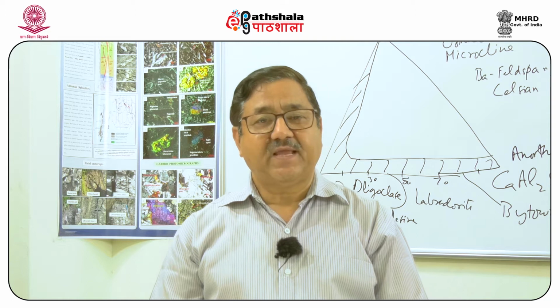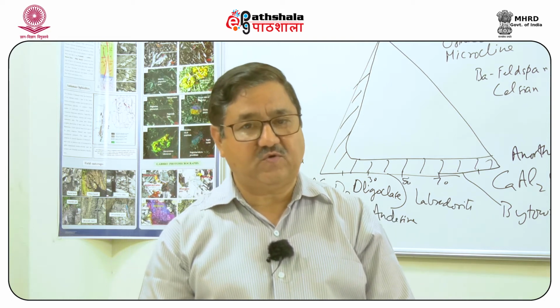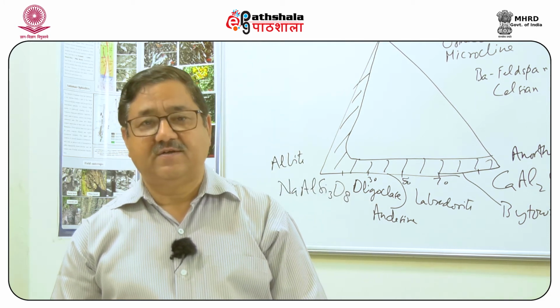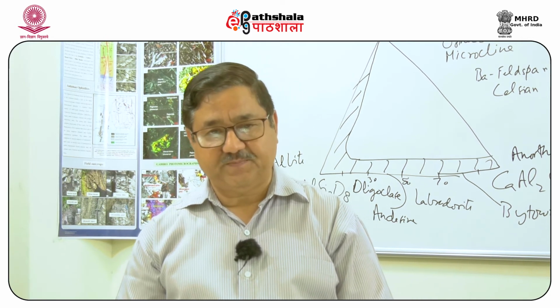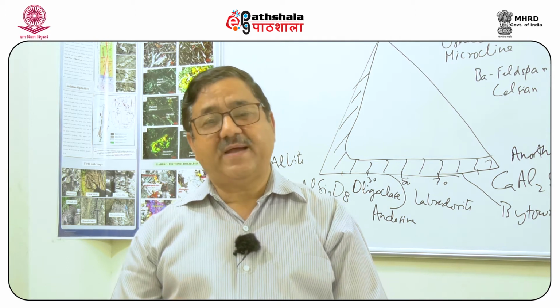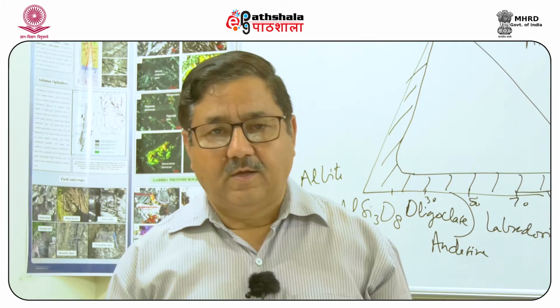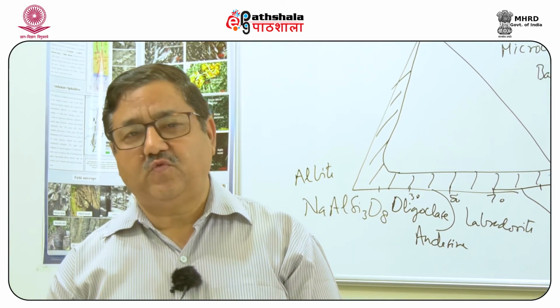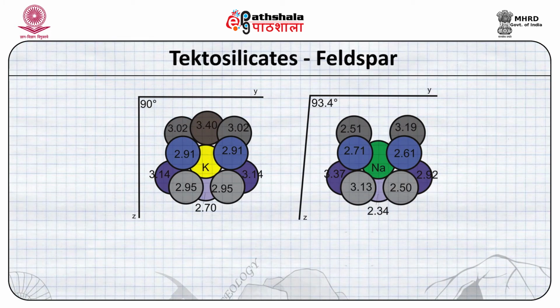These four tetrahedral sites in higher symmetry are represented as two sites, T1, T2. But in the lower forms, they represent four tetrahedral sites, T1, T2, T3 and T4. So, as you can see, the structure is beautifully controlled by the way in which the tetrahedra are arranged. We see this very beautifully illustrated in the two figures of high sanidine and high albite. In the first figure, we see potassium surrounded by oxygen atoms. Now, there are numbers written there. The numbers represent the K-O bond distances, and they are written in angstrom units. The first part of the figure, if you see, the two axes on the sides mark an angle of 90 degree between them, indicating this to be a monoclinic symmetry.